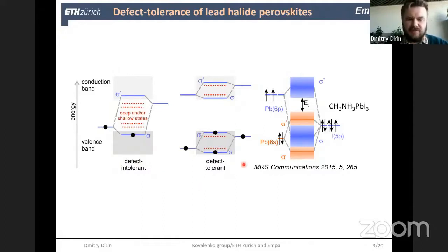But we can imagine a hypothetical case. Then the top of the valence band is formed by antibonding orbitals, and the bottom of the conduction band is formed by bonding orbitals. In this case, vacancies or dangling bonds will not create trap states within the band gap. And in 2015, it was shown that methylammonium lead iodide and in general lead halide perovskites represent such a case, at least partially. And in this case, the top of the valence band is formed by hybridized orbitals of antibonding orbitals.